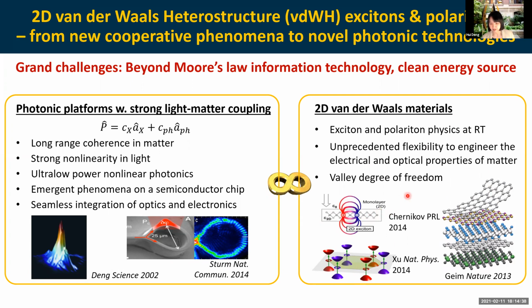They have a bunch of other very unique properties as well. Another extremely nice thing about these materials is that they can be peeled off with Scotch tape. You buy a commercial crystal, go to the lab, and then you just need to work hard to make the best crystal possible, rather than spending multiple millions of dollars and many decades on the fabrication required for conventional materials. That makes them extremely versatile, and you can also combine multiple layers to make heterostructures.